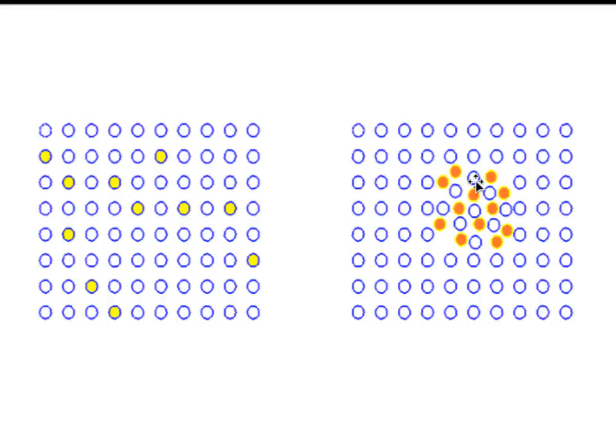dislocations. Now it's very important that the distances between these particles are small. To get a really strong effect, we should have a short distance between the particles. As it is a limited amount of volume fraction of the material that can be precipitated in the system, it must be so that every particle needs to be rather small. That's the trick when you want to do these heat treatments. It's very important to avoid that the particles grow too large.